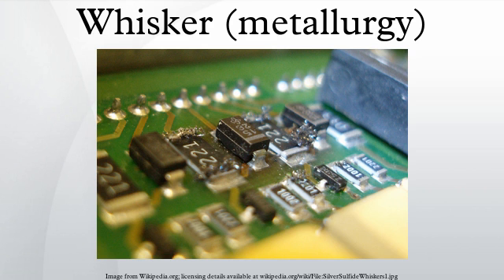Millstone Nuclear Power Plant. On April 17, 2005, the Millstone Nuclear Power Plant in Connecticut was shut down due to a false alarm that indicated an unsafe pressure drop in the reactor's steam system when the steam pressure was actually nominal. The false alarm was caused by a tin whisker that short-circuited the logic board which was responsible for monitoring the steam pressure lines in the power plant.